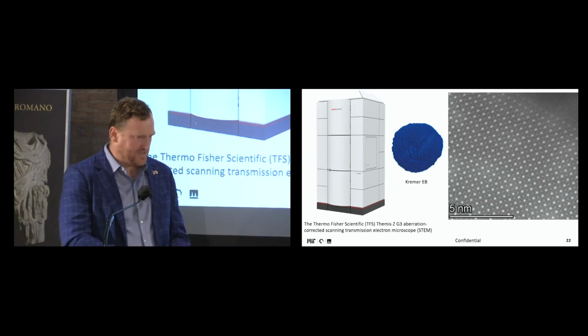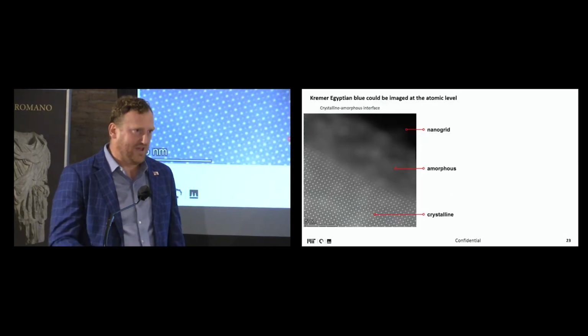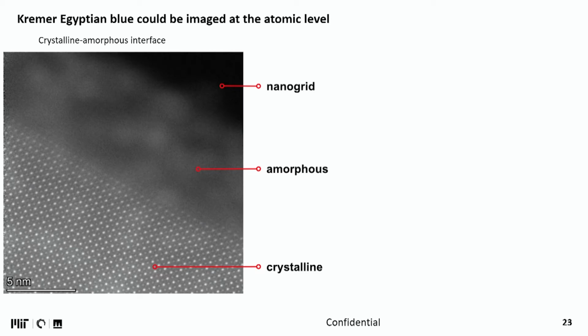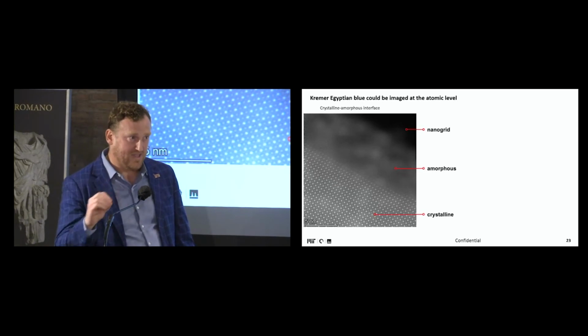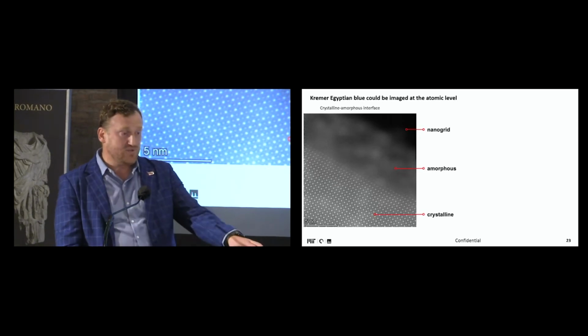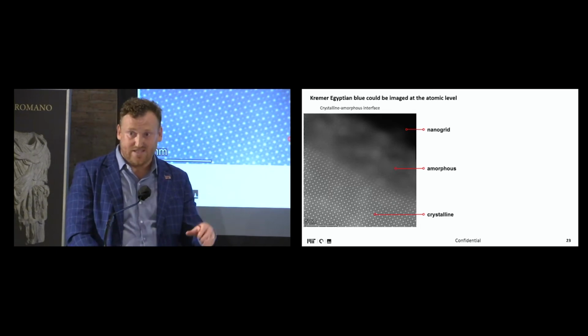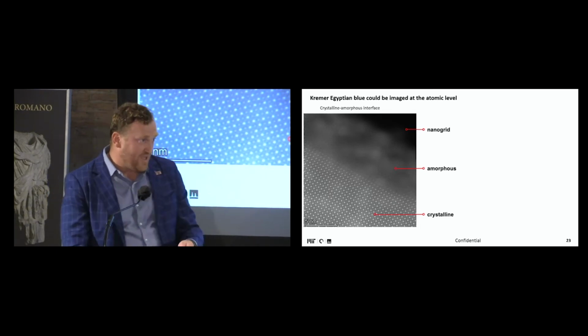And what else did we do here? What we really noticed, and this looks like a standard property, is that every time that you have a crystal, so these atoms here, there is a border interface where then it turns into amorphous. And this, if it's true, and if it becomes systematically present in all Egyptian blue samples, might be a way to actually look into original materials that were used in production, because this Egyptian blue was crystallizing while we were cooling our Egyptian blue in the workshop.